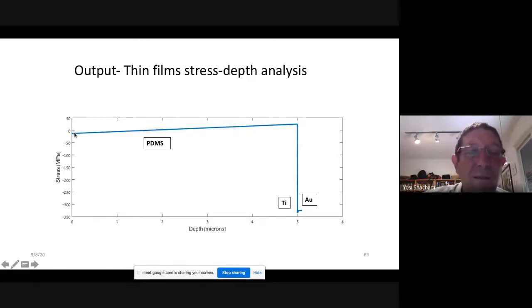And as expected, the stress in the PDMS is very, very small. You see, it's less than 10 megapascal. But then, to our surprise, we got in the gold a stress of more than 300 megapascal, huge stress on the gold, which we did not expect. And what we found out is that PDMS is a very soft material, but it's incompressible. And the problem is the gold and the PDMS have different coefficients of thermal expansion. So when you heat them and cool them, the PDMS is applying a huge force on the gold.